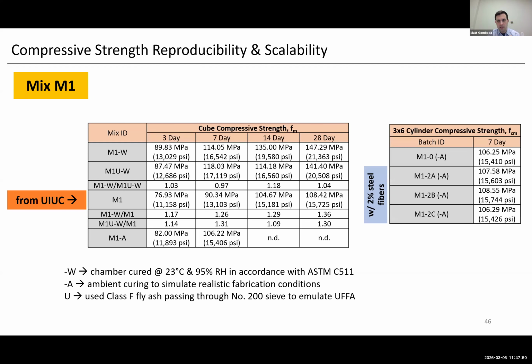And you can see the compressive strengths here, the cube specimens in the table on the left, and then the cylinder specimens there on the right that we did at the larger scale, the last three of which had the 2% steel fibers in addition, and the first ones that we did and the cubes did not in this case. So just a little bit of looking at the variation here. So the average of the specimens done at the 3x6 scale versus the cubes were within about on average 6% difference. And again, there's not fibers, but also we recognize that the fibers don't have a substantial role in the compressive strength. We're not evaluating tensile ductility right now, but we just wanted to make this first comparison.